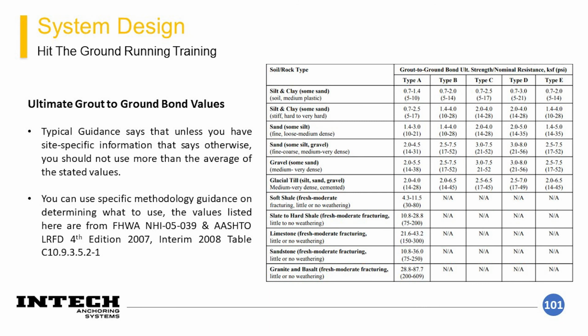So the table on this slide gives values of what we typically use for ultimate grout-to-ground bond for soils. You can match up the types of soils in each layer with this table to determine how much ultimate strength you should use for your bond values. So the column for type A is a conventional gravity grout system, whereas for the hollow bar system, you should use column E. So you can see the values for column E typically have higher values of bond strength based on it being installed with a pressurized grout. This is especially notable with sand layers.